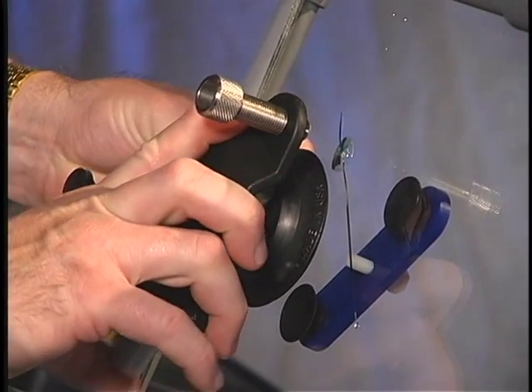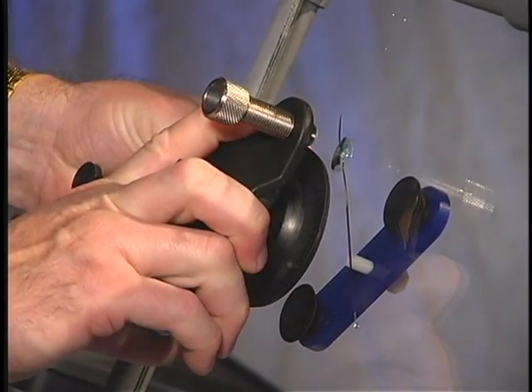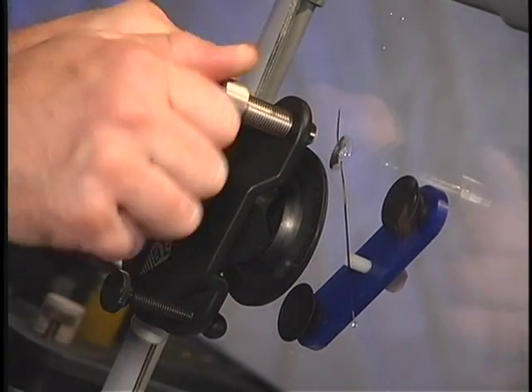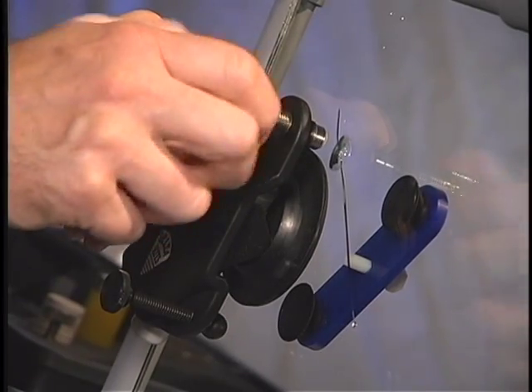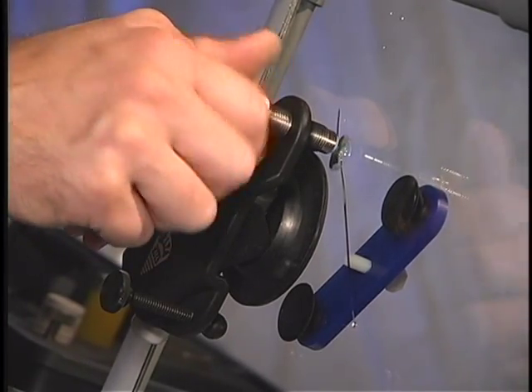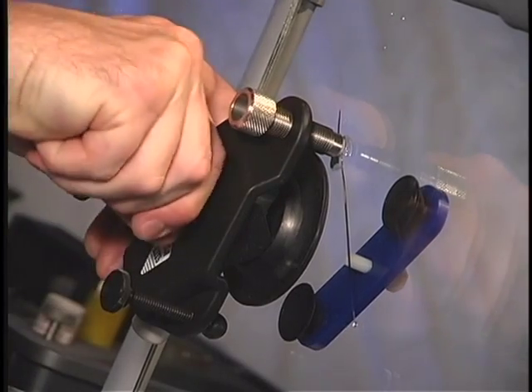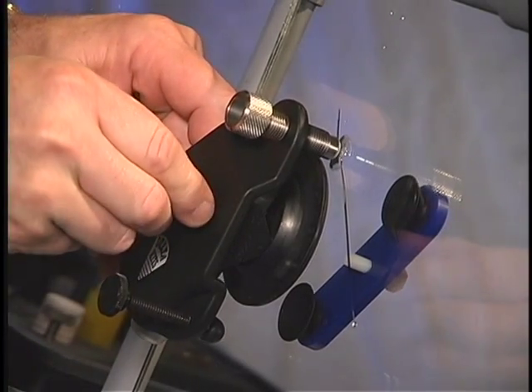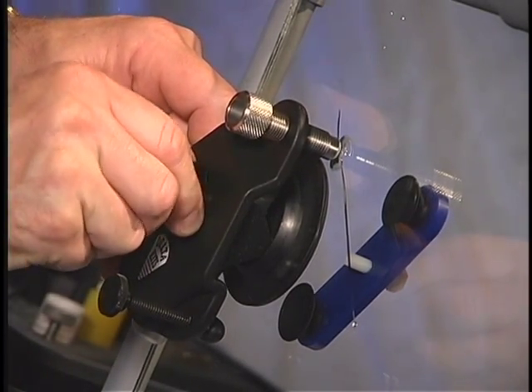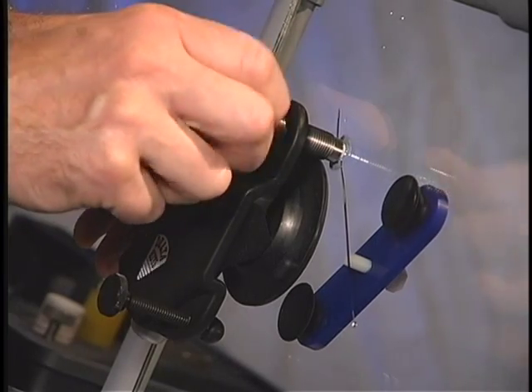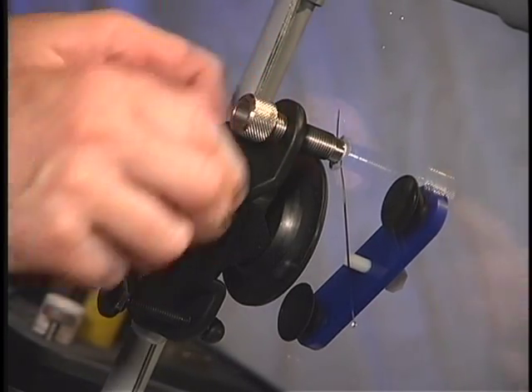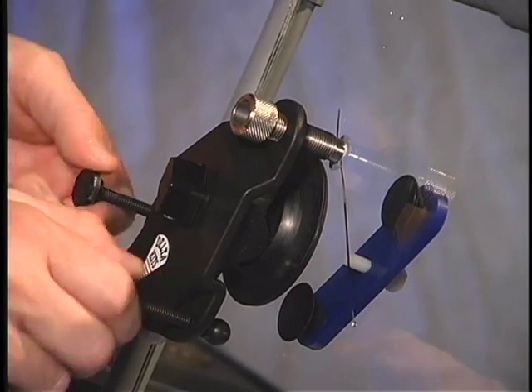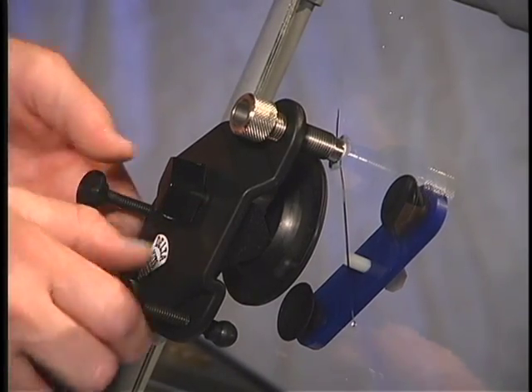The second most common reason for this problem is putting too much pressure on the windshield when affixing the bridge. If the injector is over-tightened, the glass will flex in, and the cracks will close just as when overheated. To eliminate this problem, once the injector seal has made contact with the glass, rotate the injector one more complete turn and no more. Then make your final leveling adjustments with the rear adjusting screws.